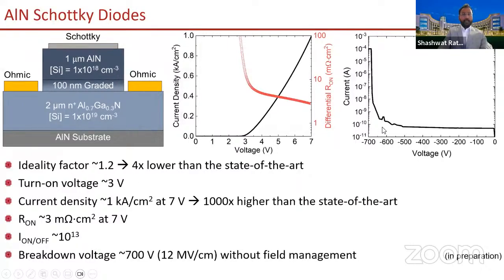Here the important thing is the ideality factor in these devices. So this should be close to 1, and the previous best value out there in the literature was 5. This is how difficult it is to make power devices based on aluminum nitride, and we were able to show values which are close to ideal, with a near ideal turn on voltage, and we were able to pass 1 kilo ampere of current per centimeter square of the footprint. So this is a very good value, 3 orders of magnitude higher than the best reports out there. So this really testifies that our aluminum nitride is conducting in its on state.